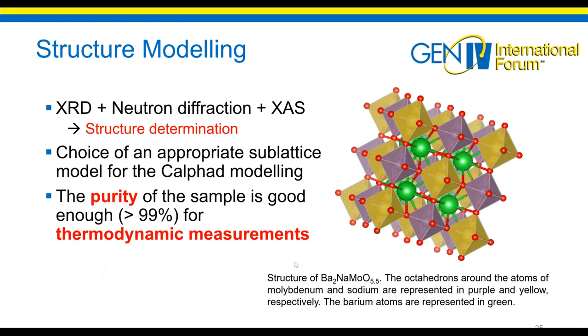Okay, so combining all this information, so X-ray diffraction, neutron diffraction, and X-ray absorption spectroscopy, you can have a precise determination of your structure like this. So this is really how the crystal looks like in our quaternary compound with sodium, molybdenum, and barium atoms and oxygen. And thanks to this structure representation, you can choose the appropriate sublattice model for the CALPHAD modeling, which is basically how you will model your structure in the software.